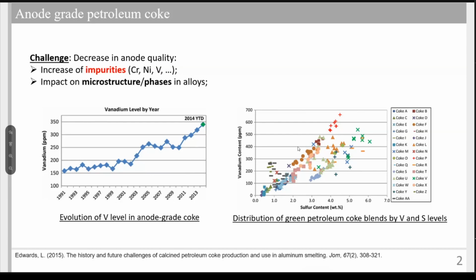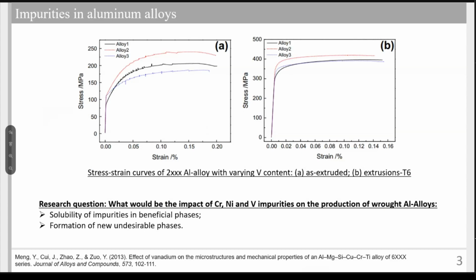And as well, the blends that are available for primary aluminum production have increasing contents of vanadium and other impurities. Such impurities are not harmless in the final product of aluminum alloys. In one study, you can see the stress strain curves for a 2000 series alloy, where the vanadium content has changed the mechanical properties. Because of the demand for increasingly high performance alloys and the need for, for example, recycling, the content of impurities must be tightly controlled. This leads to my research question: what is the impact of chromium, nickel, and vanadium impurities on the production of wrought aluminum alloys, especially regarding the solubility of impurities in beneficial phases, and the formation of new undesirable phases?